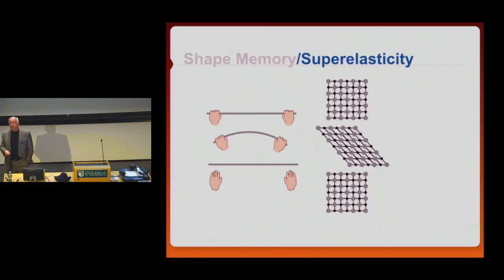Stress-induced martensite, and we call that superelasticity because the amount of elastic recovery that you can get is much higher than in stainless or any other metallic material for that purpose. It's about 10 times higher than steel elasticity, and that's why we call it superelasticity. It's a little bit of a marketing term because I think the scientists have called it pseudo-elasticity. But when you sell something and you say this is pseudo-elastic, then you as an engineer would say, I'm not going to buy anything that's pseudo only. So that's why we called it superelasticity, and it goes much better, I can tell you.